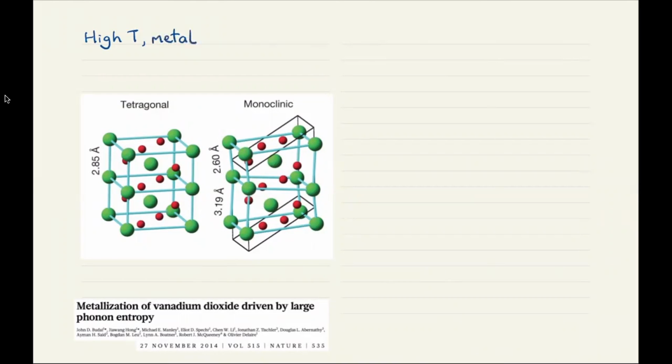And here the structure has perfect, identical octahedra of vanadium six coordinated by oxygen. And all of the vanadium-vanadium bond lengths are all the same, or the vanadium-vanadium distances, in this direction are all equal.